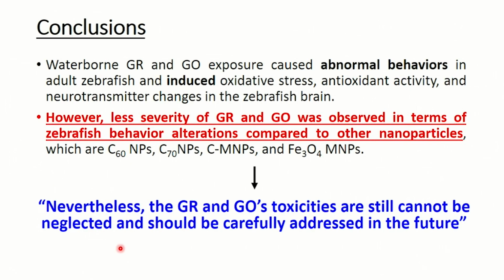To conclude, waterborne graphene and graphene oxide exposure cause abnormal behaviors in adult zebrafish and induce oxidative stress, antioxidant activity, and neurotransmitter changes in the zebrafish brains. However, less severity of graphene and graphene oxide was observed in terms of zebrafish behavior alterations compared to other nanoparticles, which are carbon-60 nanoparticles, carbon-70 nanoparticles, carbon-coated magnetic nanoparticles, and magnetic nanoparticles. Nevertheless, graphene and graphene oxide toxicity still cannot be neglected and should be carefully addressed in the future.